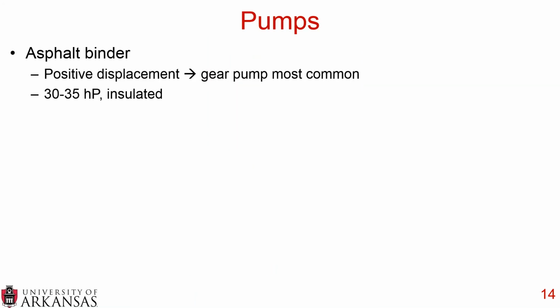Something's gotta move this material around, and those are pumps. So for asphalt binder, you usually use a positive displacement pump, and a gear pump is the most common. And they're usually 30 to 35 horsepower, and you want to make sure those are insulated because your asphalt binder needs to be kept hot at all stages. You don't want it cooling off in the pump because then you'll just have a gummed up pump.